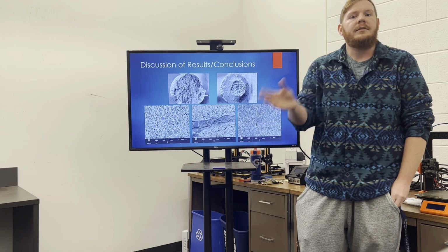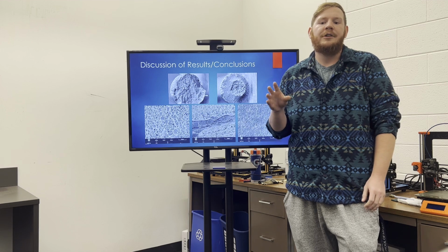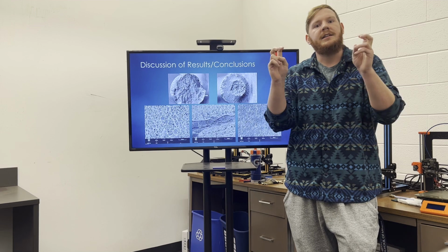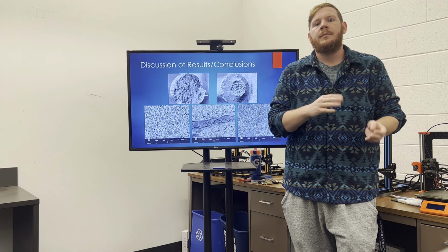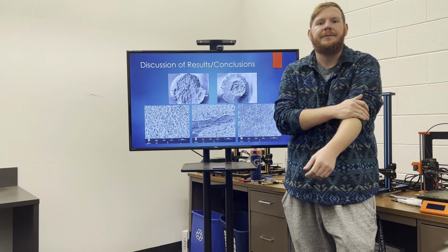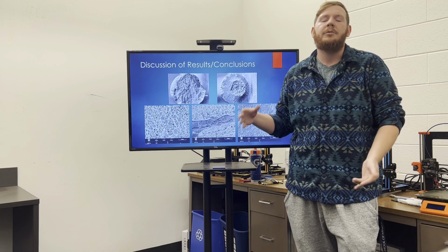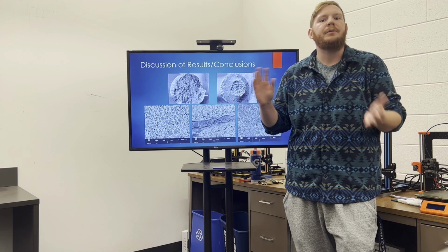Using this data and the results from prior, we believe that this material didn't actually ever reach its H900 heat treatment state. We believe that this is still in a condition A state, where that's right after the solution heat treatment. I believe for this was 1900 Fahrenheit for half an hour. And in this state, the reason we believe this is it is prone to variety of fracture and unpredictability in the precipitate location and methods of failure.